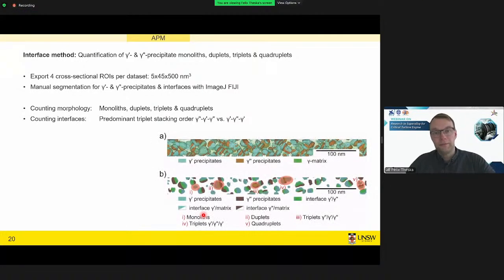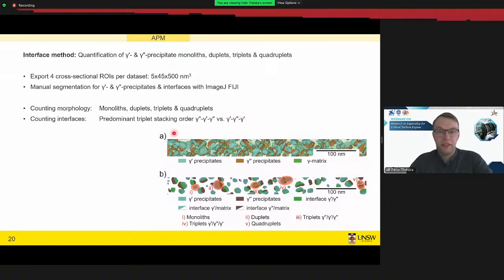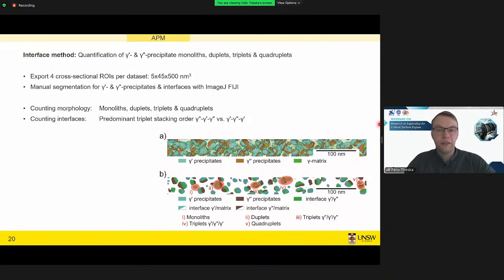So we have reconstructed our data. We now can represent these particles reliably, now we can start doing some quantitative analysis of these atom probe data. So for example, in this figure A, we see the side view of a three-dimensional data set, and that's quite difficult to analyze if we want to know how are these co-precipitates stacked together. What we can do to make it a bit more simple is take some cross sections. We just cut a slice out of our data and then start segmenting what's gamma prime, what's gamma double prime. So we get a much simpler map as in figure B.